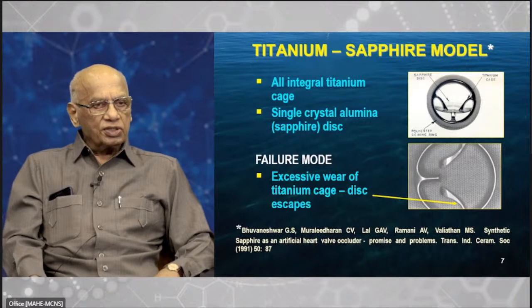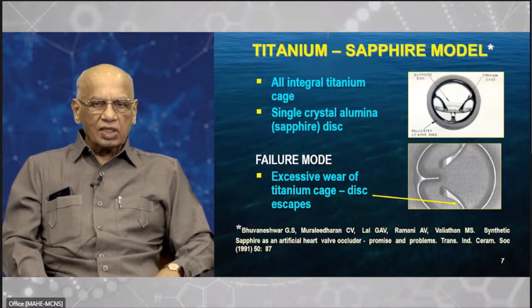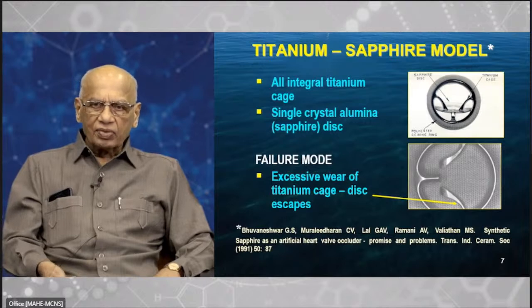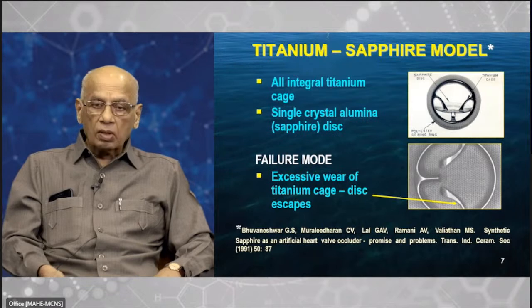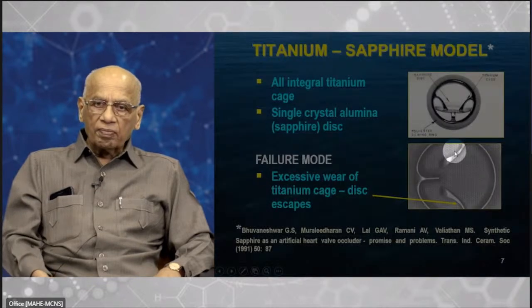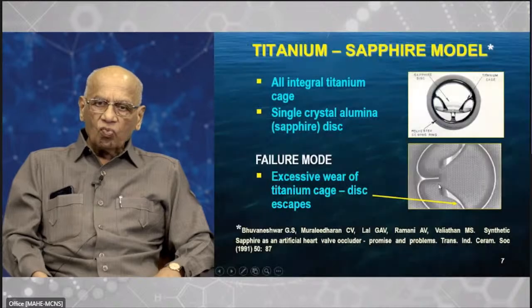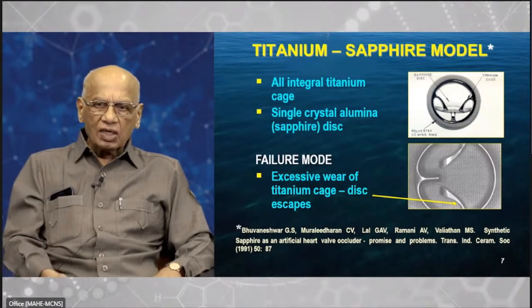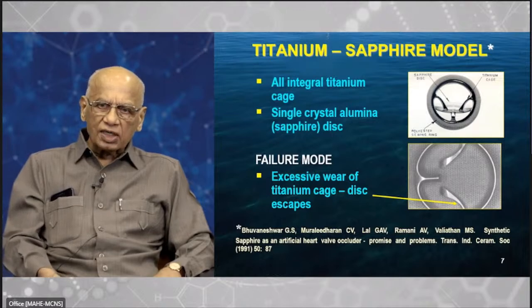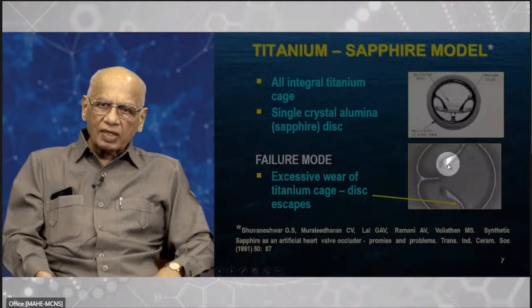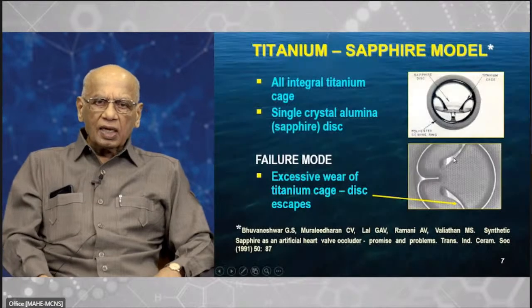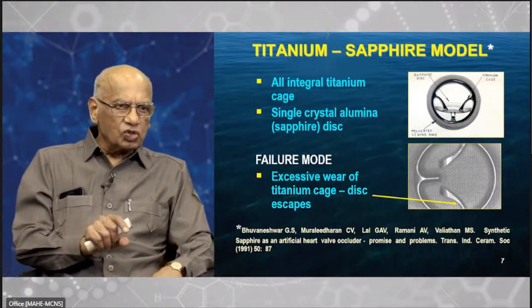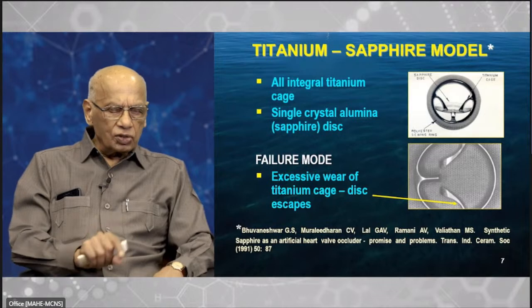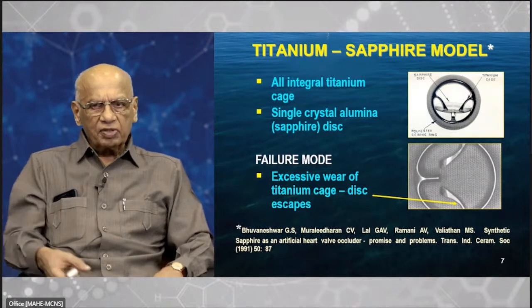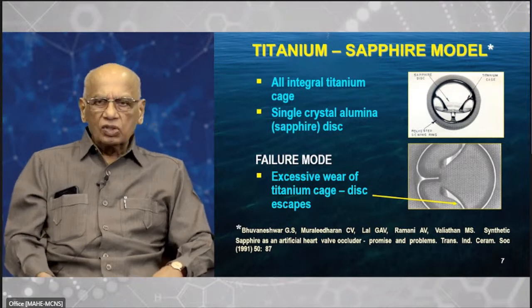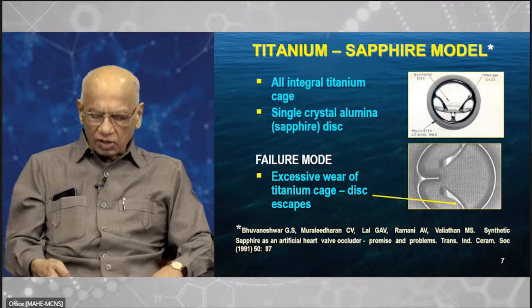Now, when we tested this all-integral cage of titanium and single crystal alumina, look at the bottom. Here, you can see the wear, because this sapphire is tilting against these 2 struts and they are simply wearing. A lot of wear, and the disc actually escapes, because the gap where it is lodged should be very small. And if the gap becomes very large, as the struts begin to wear, then it escapes from there. So this model was not acceptable. So we moved to the third.